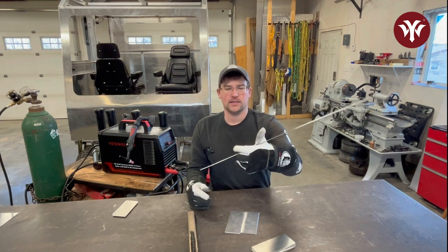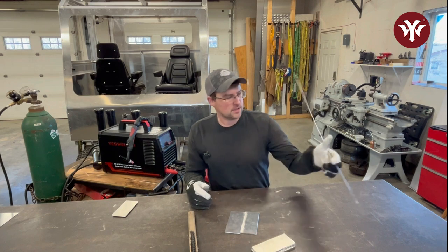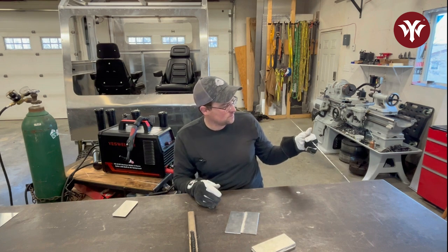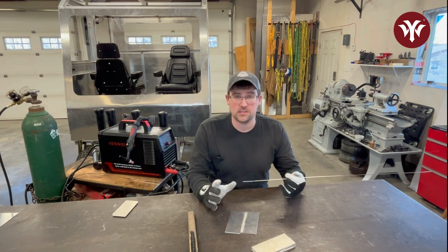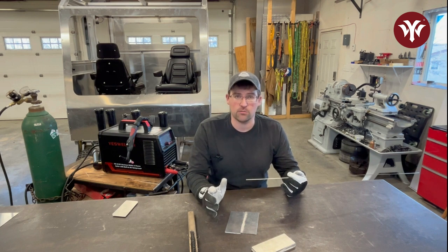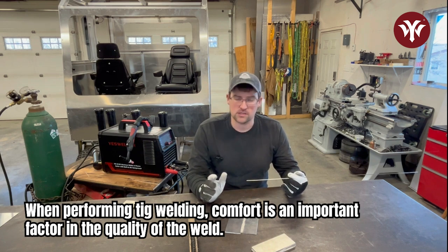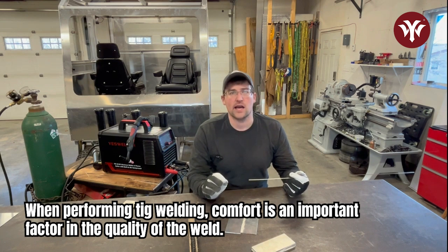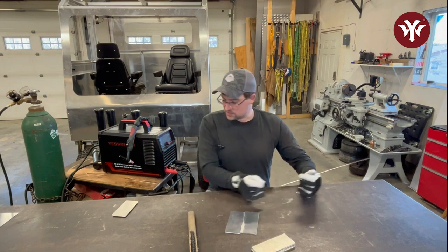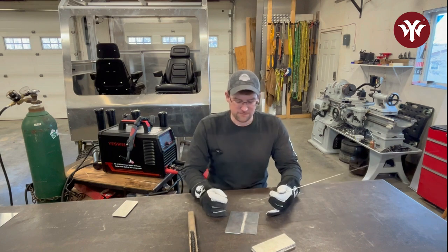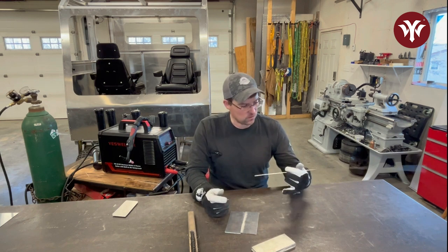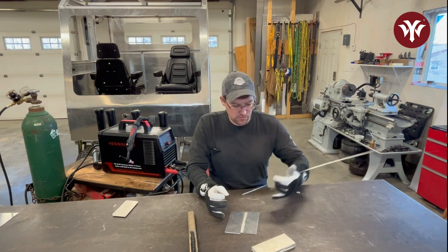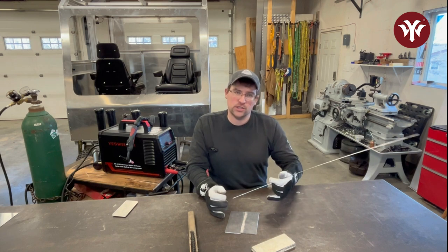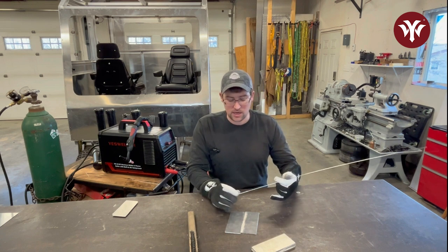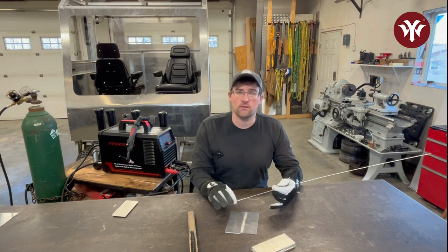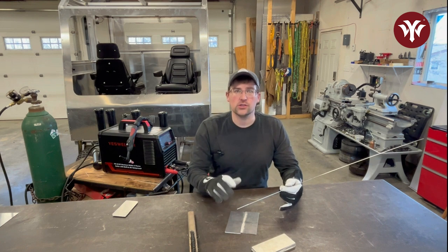At first, you can hold the rod however you want and try dabbing in, but something to practice is feeding the rod with one hand. It's a bit of a hard thing to learn, but when you set up, one of the other things I'm going to talk about when you're welding is being comfortable. And when you're TIG welding, comfort is going to be a huge factor in you getting the weld quality you want. So test your weld passes, get comfortable, take a breath, and then when you're feeding that rod, if you're moving your hand all the time, you're going to push in too much, you're going to pull away. The other thing you want to do is always try and keep that tip of your rod close to your TIG torch.